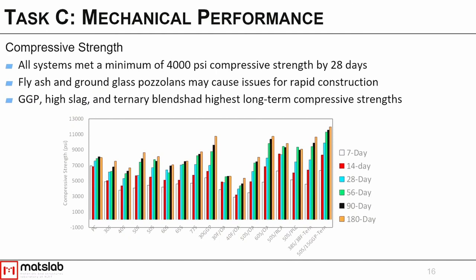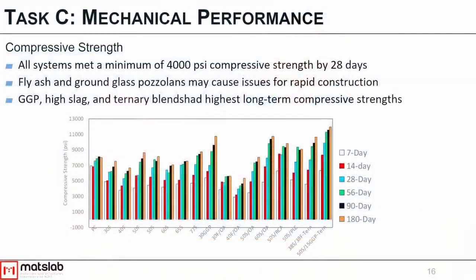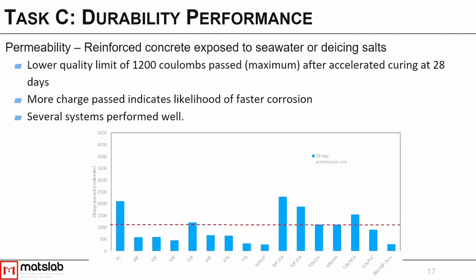And in some cases, we actually had 56 and 180-day strengths up above 11,000 PSI for a mixture with less than 400 pounds per cubic yard of Portland cement. So we actually got great strength results out of these systems. Our biggest issues were with our optimized aggregate systems, and this is sort of a technology that we need to dive into a little bit more to understand how to better design those mixtures in terms of strength. But overall, we did pretty well.